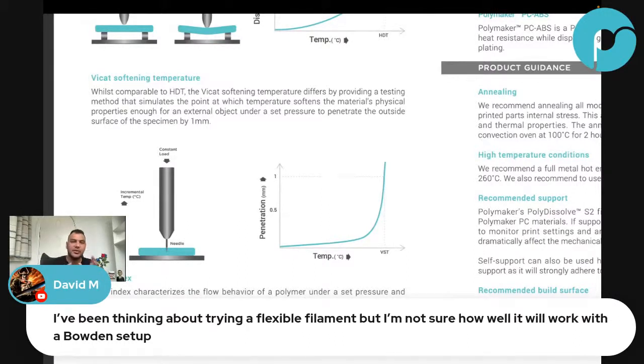Okay, so I was saying, to print flexible, you either need to decrease the pressure that you need to extrude, or you need to increase the pressure itself. So why Bowden? Usually people say indirect extruders are not very good because it's even harder to transfer the energy from the extruder to the nozzle. So when I print flexible on a Polymaker or Ender 3, I use crazy high temperature. For example, I print TPU at 240 or 250 because then I only require a small amount of pressure in order to extrude my material. Okay, does that make sense?